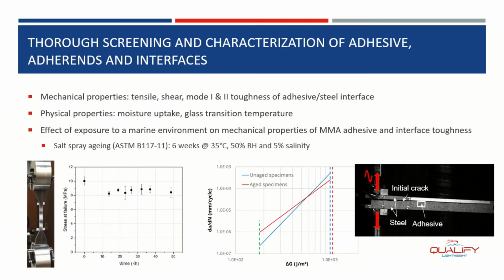Both aged and unaged specimens need exactly the same energy to initiate crack extension, and both start or stop at approximately the same critical toughness for final failure. Those are the dashed lines that you see on the graph. The red curve indicates that the crack propagation rate at the start of the test at lower toughness values is a little bit larger for the aged specimens, but near the end they reach approximately the same, with the aged ones a little bit slower in further crack propagation near the critical energy rate. So quite comparable, let's say, basic properties with only minor reductions in mechanical behavior.